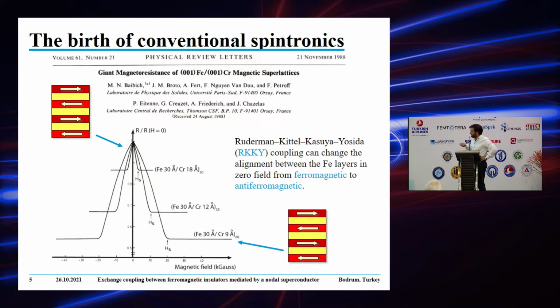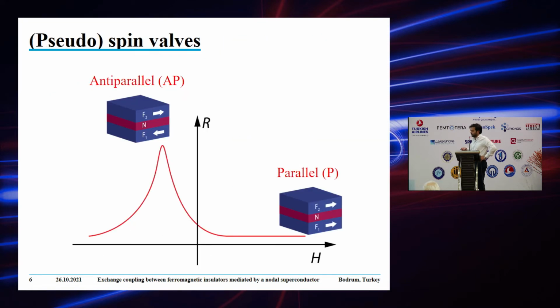But in zero field, there is this antiferromagnetic coupling between the iron layers, and therefore the resistance reaches a maximum. So this is a system with two states: a low resistance state, which is the parallel state, and a high resistance state, which is the antiparallel state, which is exactly what a spin valve does.